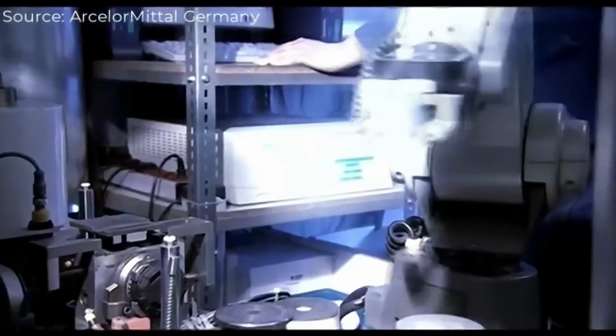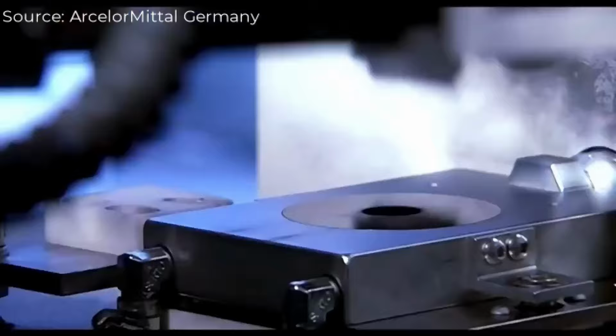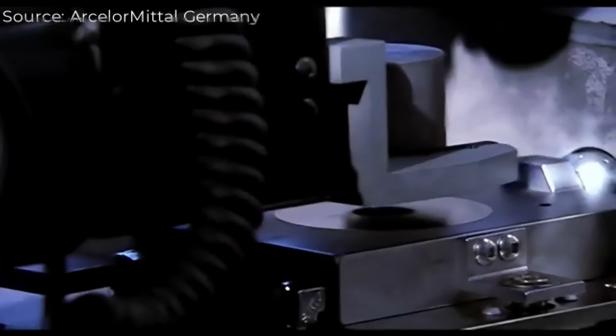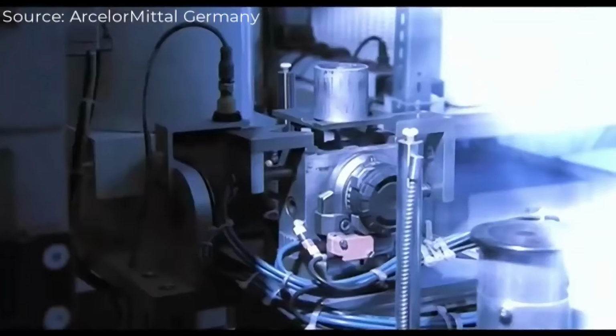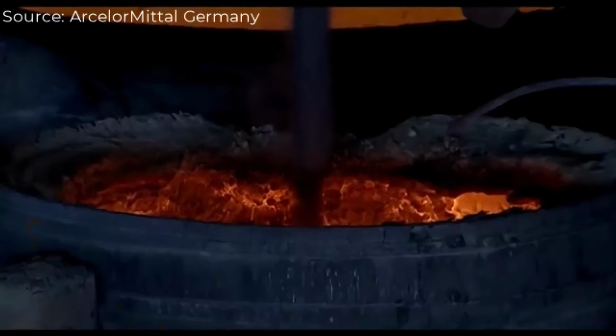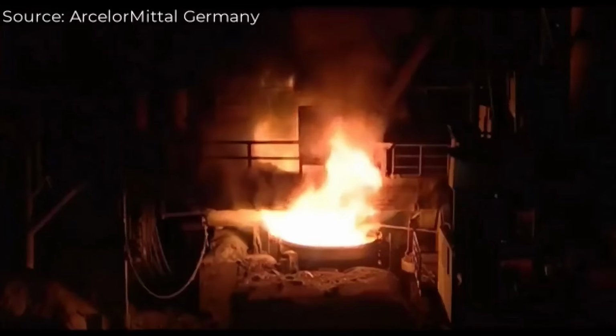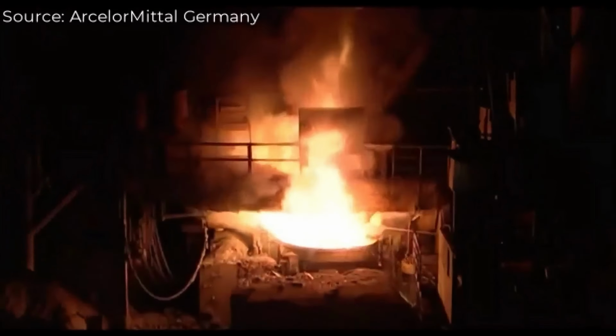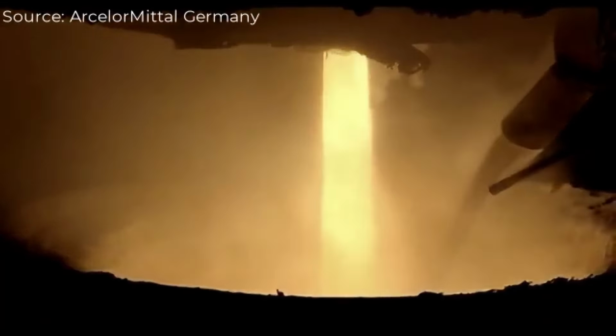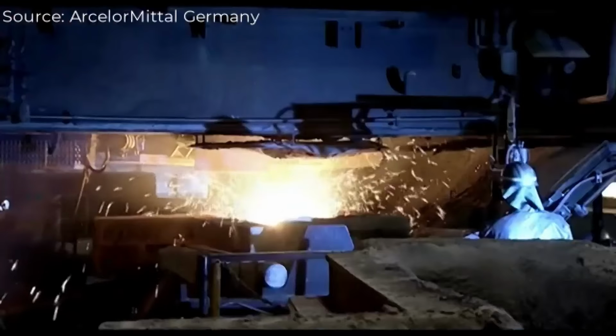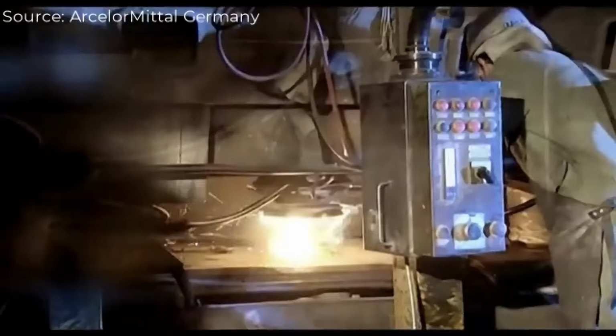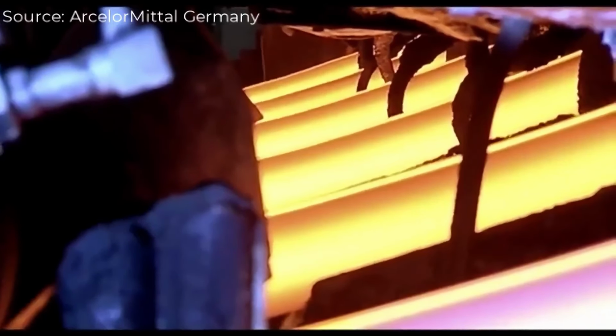The iron ore is processed using direct reduction technology, using natural gas at 1000 degrees Celsius, converting it into almost pure sponge iron, significantly reducing CO2 emissions. In the electric arc furnace, sponge iron and scrap are melted by electric current through graphite electrodes, reaching temperatures of 1600 to 1630 degrees Celsius.